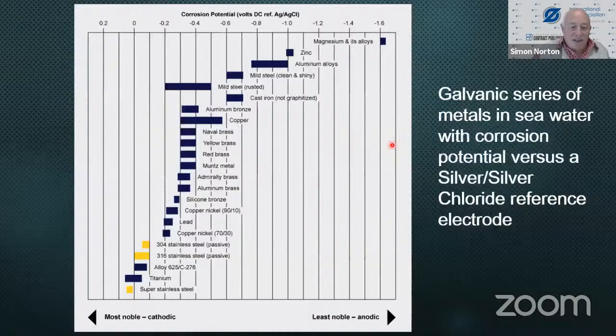If you look at this more detailed Galvanic Series in seawater, you'll see across the top of the diagram the voltage measured against what's called a Silver/Silver Chloride electrode. It's a simple thing. It's a reference electrode. So we compare the material in seawater against a reference. And there on the right top side, you can see zinc. There you see clean, shiny, mild steel sitting just below 0.6 of a volt. In electrochemistry, we tend to work more in millivolts. So we're sitting somewhere between 550 and 600 millivolts, with zinc sitting up here.